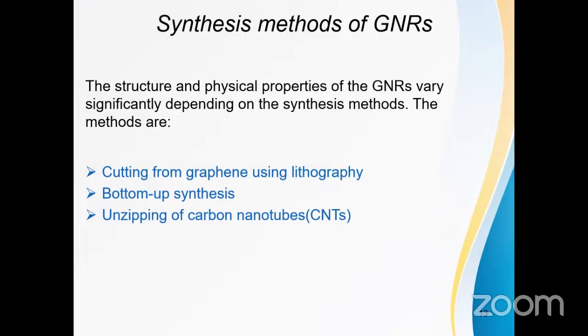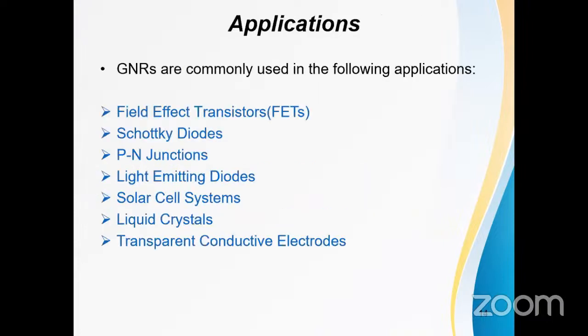The second method is bottom-up synthesis. In bottom-up synthesis, the structures are assembled from their subcomponents in an additive fashion. The third one is unzipping of carbon nanotubes. GNRs can be produced by unzipping or axially cutting nanotubes. In one such method, multi-walled carbon nanotubes were unzipped in solution by the action of potassium permanganate and sulfuric acid. In another method, GNRs were produced by plasma etching of nanotubes partly embedded in a polymer film.